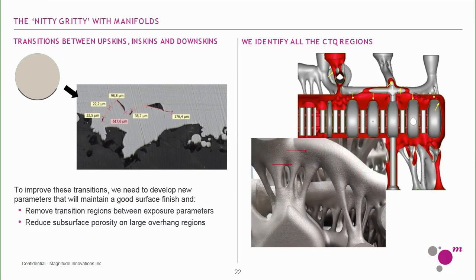So then, after we did the parameter development, this is what we got. You can see that the transition between these downwards facing areas and the upwards facing areas is very homogeneous, and this is straight out of the machine. And then we also, of course, tested those regions to make sure that the porosity is good, and it was. It was actually, I didn't expect this, to be honest.